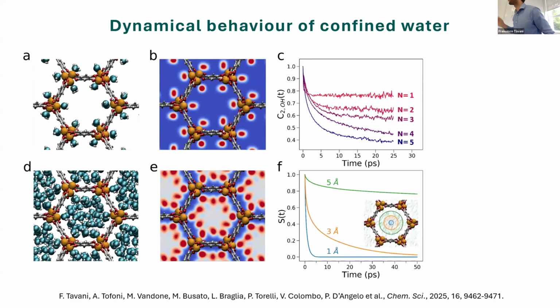And let's say to conclude this work, we also ran some calculations to study the dynamical behavior of confined water as a function of water loading. So here I am basically considering just the systems with the lowest and the highest water loading, so n equals 1 and n equals 5. And you may see in panel C a plot of the reorientational correlation function for water.